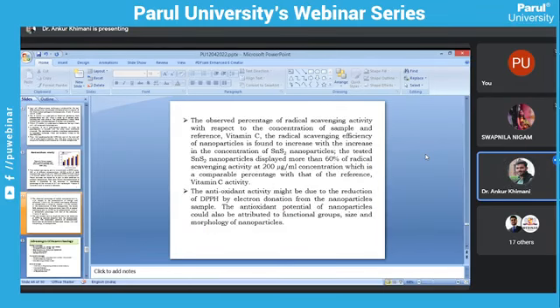So observe the percentage of radical scavenging activity with respect to the concentration of the sample and reference. The radical scavenging efficiency of the nanoparticle is found to increase with the increase in the concentration of the SnS2 nanoparticle. The tested SnS2 nanoparticle displays more than 60% radical scavenging activity at 200 microgram per ml concentration, which is a comparable percentage with that of reference vitamin C activity. The antioxidant activity might be due to the reduction of DPPH by electron donation from the nanoparticle sample. The antioxidant potential of the nanoparticle could also be attributed to functional group, size, and morphology of the nanoparticle.